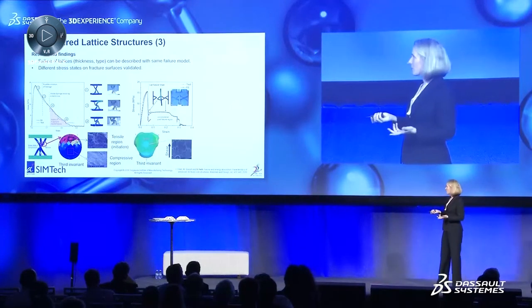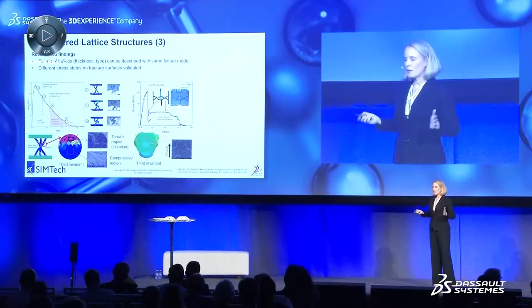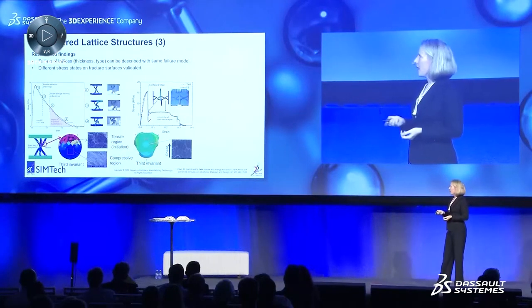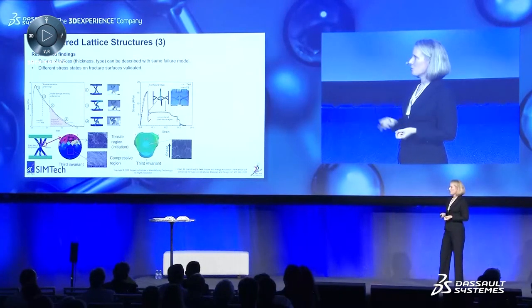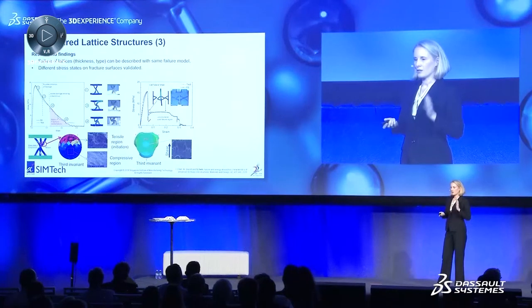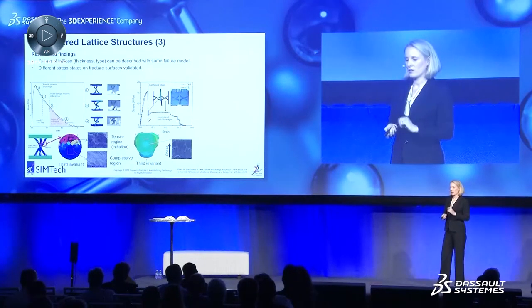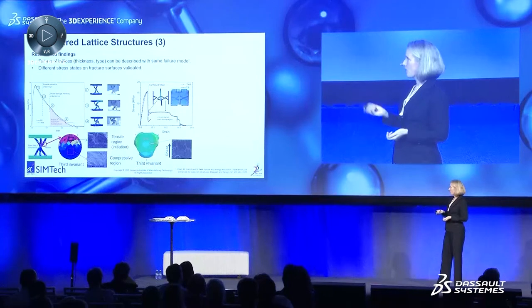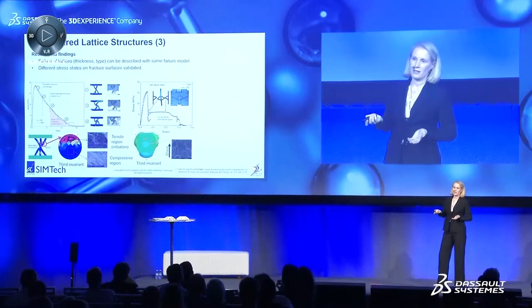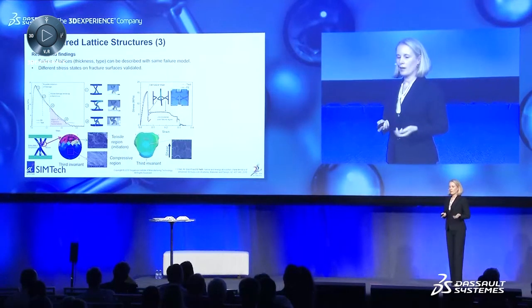We did the same thing for shear, and exactly the same material model, no changes. And we could see again, we could predict this very well. And the surface in this case, we could see nice shear patterns. And also the numerical analysis showed that this was shear. But of course, this is not enough.